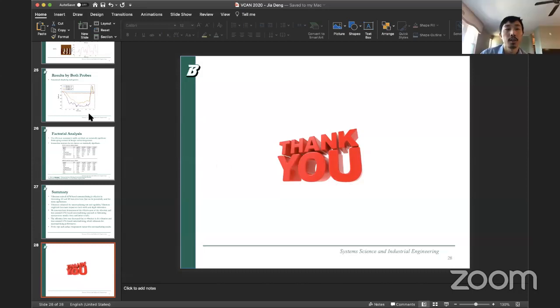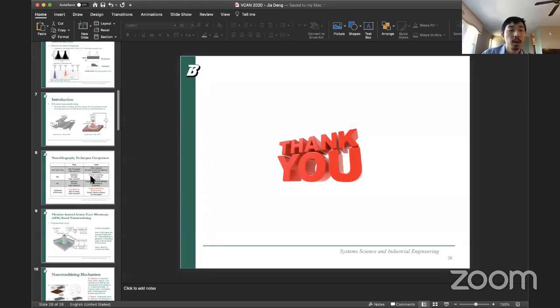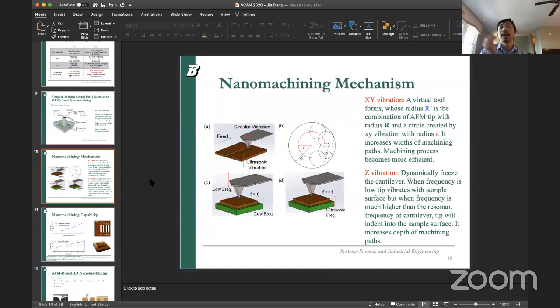Okay, thanks for your question. In terms of the frequency relationship here, the XY vibration frequency doesn't affect the results too much. The only capability is to tune the width. If we apply the nanomachining frequency at about 2 kHz, it coordinates very well with the machining speed. So for each machining cycle, you only slice about 1 nanometer in the machining direction. So it will have a smaller machining load for each vibration.